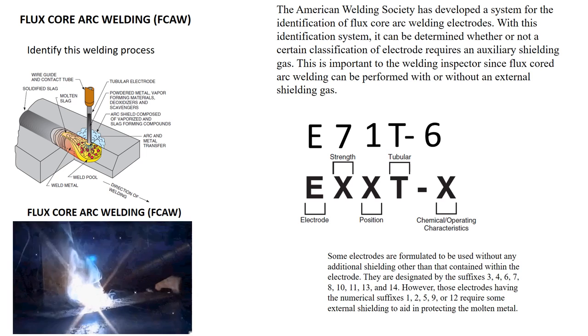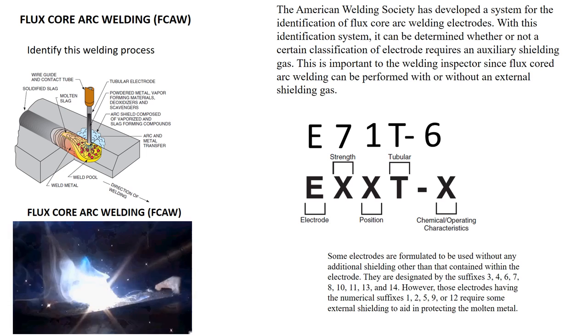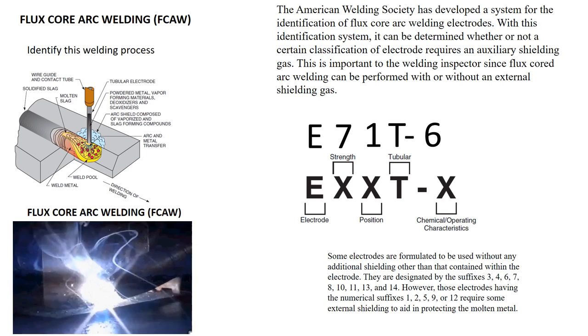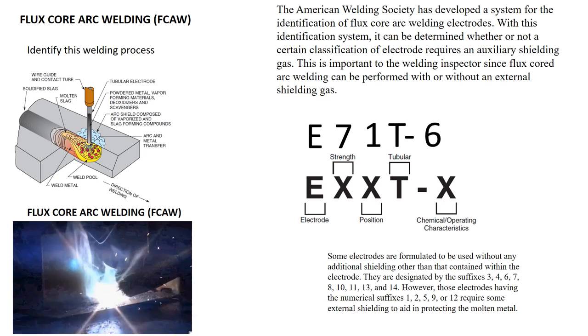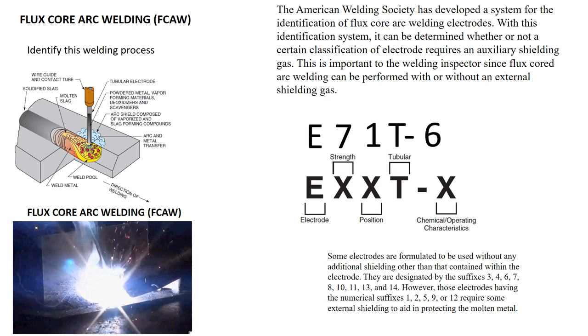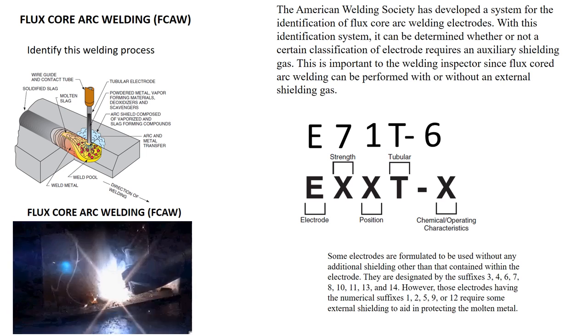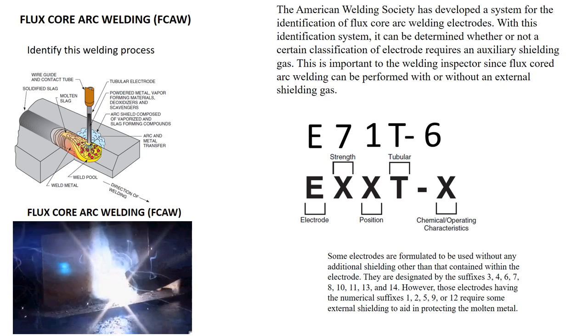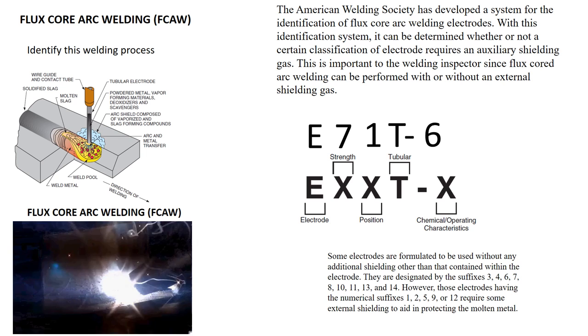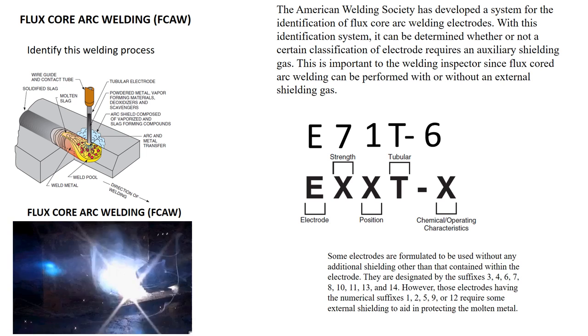Some electrodes are formulated to be used without any additional shielding gas, other than that contained within the tubular electrode. They are designated by the suffixes 3, 4, 6, 7, 8, 10, 11, 13, and 14.